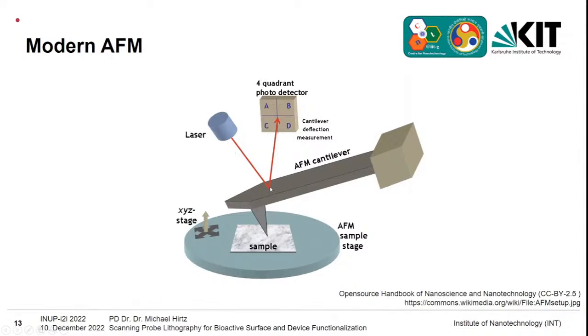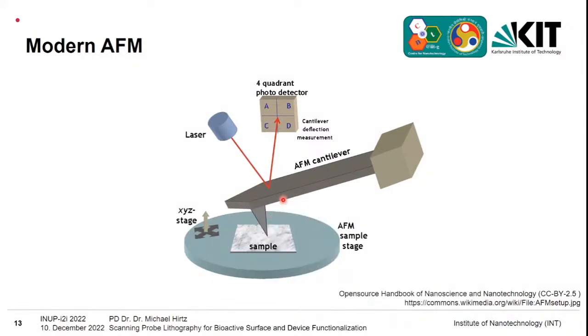So in modern AFMs, this is not done by an STM anymore. So there is not this double feature, let's say, but modern AFMs usually use a laser that is reflected from the AFM cantilever and measured far away on a photodiode. And by the modulation of this laser, you can again monitor the displacement of the tip. That means we can again scan over a sample and get our image done.